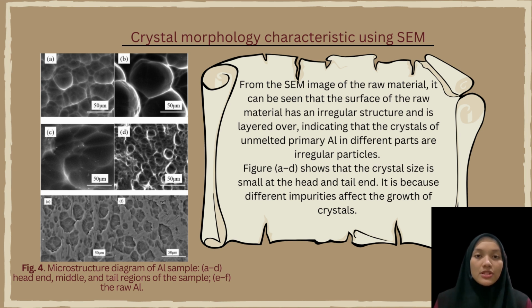From the SEM image of the raw material, it can be seen that the surface of the raw material has an irregular structure and is layered over, indicating that the crystals of unmelted primary aluminium in different parts are irregular particles. Figure 4 (a-d) shows that the crystal size is small at the head and tail end. It is because different impurities affect the growth of crystals.